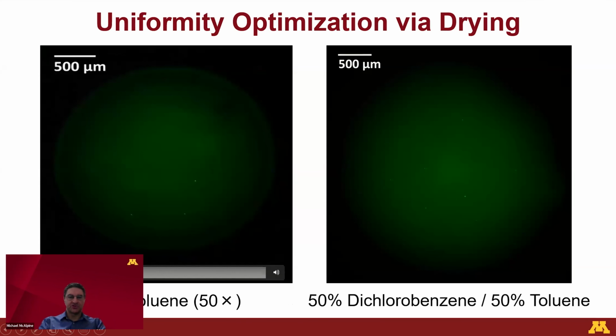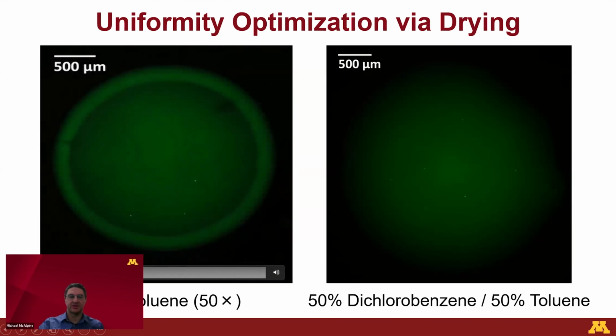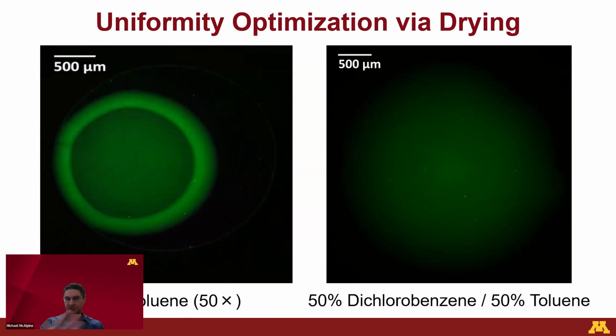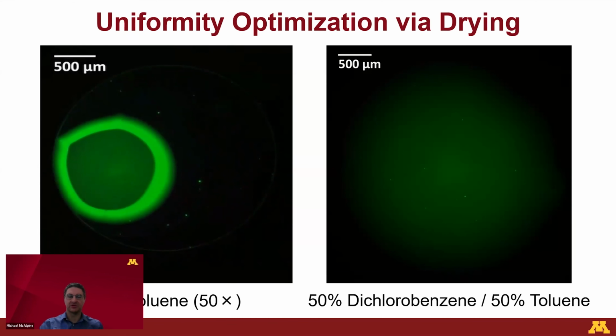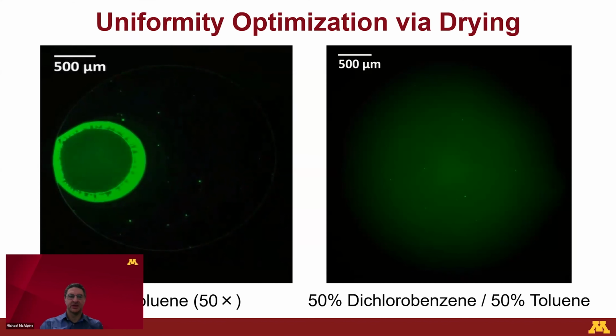Okay. So the trick here is, how do you actually 3D print a semiconductor? So what we use is semiconductor quantum dots. So these are small particles of semiconductors. So that solves the problem where we're not using a large single crystal. So therefore you can create an ink. But even then, when you deposit this ink of semiconducting particles, you can see that you don't get a nice uniform distribution of the particles. And if you're trying to make a large scale array of devices, you want to have good uniform device properties and device performance. And you're not going to get it with what you just saw there, which is the well-known coffee ring effect. Happens when coffee dries. The particles essentially, instead of being uniformly drying, they actually form a ring.